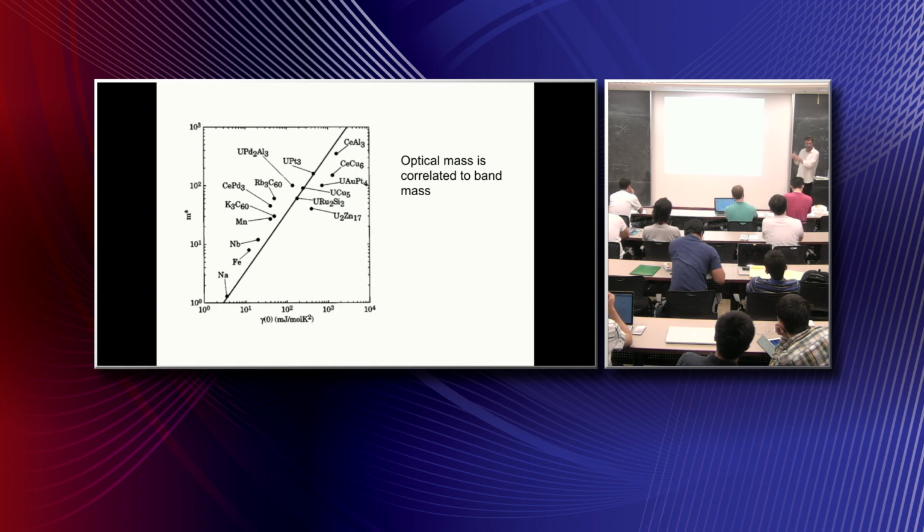And it's really a remarkable demonstration, again, of this quasi-particle concept. Obviously there's some scatter here, but there's a rough correspondence. If you assume that unit cells of materials are generally all the same size, and there's approximately one electron contributing to the conductivity per unit cell, then this rough correspondence shows indeed that things that are very, very heavy have a heat capacity which is very large, and there's this kind of linear scaling. Okay. Any questions on that?